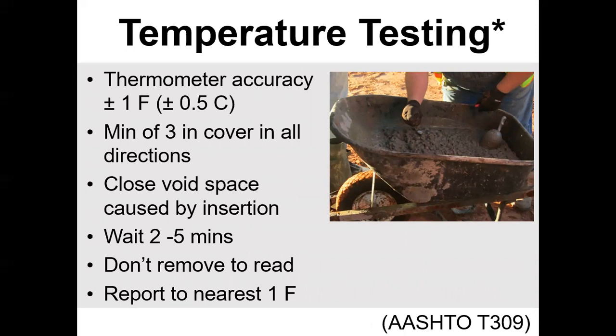The easiest test is temperature. You place your thermometer — similar to a Thanksgiving turkey thermometer — in one of the four corners of the wheelbarrow. Make sure there's at least a minimum of three inches of cover and that concrete is touching all around it. Wait at least two minutes but no more than five, and report to the nearest one degree Fahrenheit.